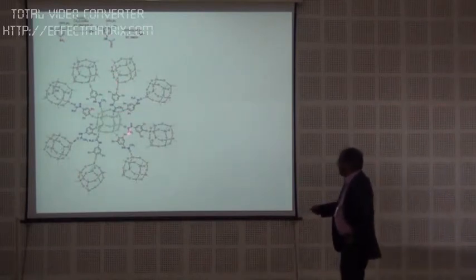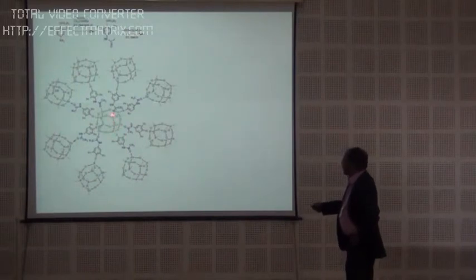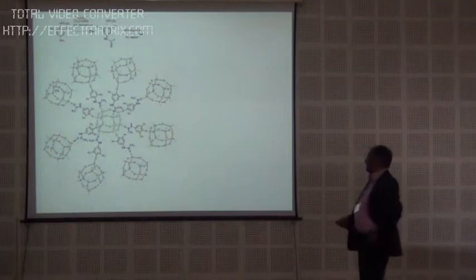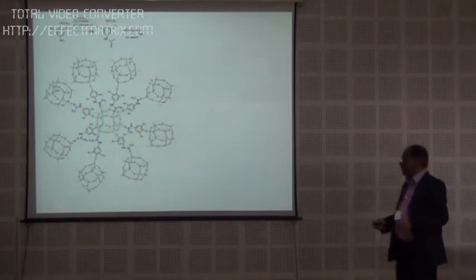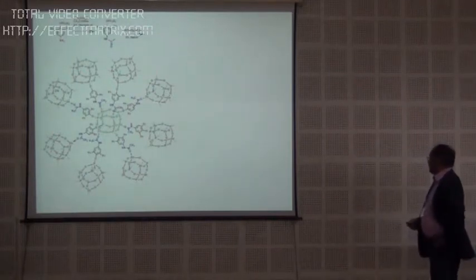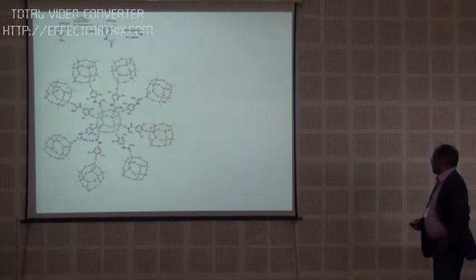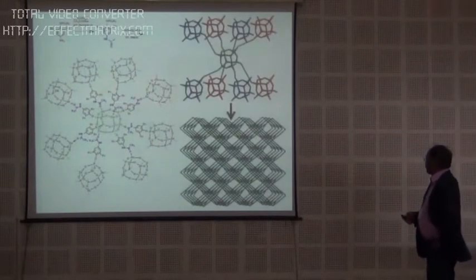So essentially each of the cubanes contains 4 coordination to the phosphorus and 4 coordination to the zinc. As a result, you have an 8 connected network. Something that has not been seen before in any of the porous solids that have been made so far. Even the MOFs contain a maximum of 6 connectivities when you have an octahedral structure. So this is how the structure looks like.